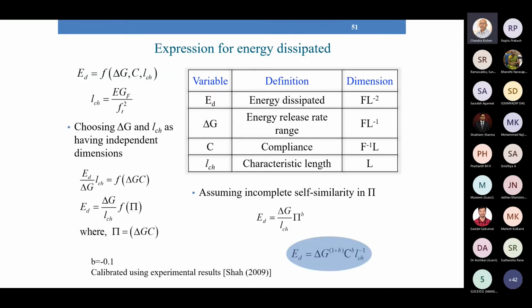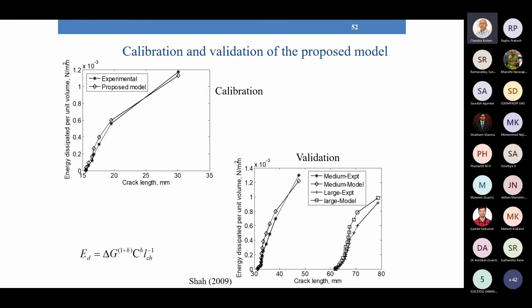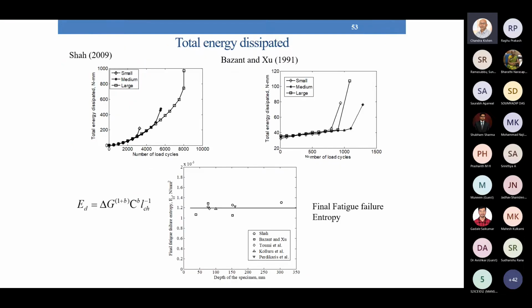So here once again, using dimensional analysis, starting from first principles, using all the variables which contribute to the rate of gain of energy or the entropy, we could establish a law for the energy dissipated. And then again, the calibration and validation is done with experimental results. And here, on the vertical axis, we have total energy dissipated versus the number of load cycles. That means for a given load cycle, the amount of energy dissipated is the same for small, medium, and large size specimens, what we see here.